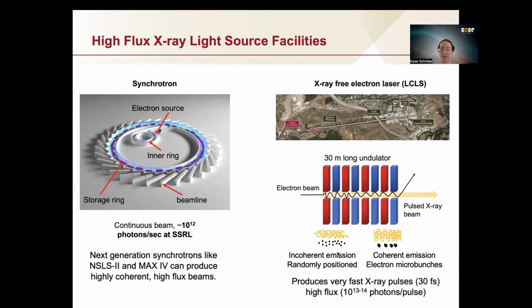What happens when it goes through this undulator is you have incoherent emission of X-ray light and randomly positioned electrons in the beam. As it goes through the undulator, the electric field starts to impart more force onto the electrons and the X-rays, and you start to see coherent emission of X-rays and also electron micro bunches that are spaced evenly. And we call this process self-amplified spontaneous emission. And when this occurs, you can get very, very fast X-ray pulses on the order of 30 femtoseconds. And you get a lot of X-rays in that pulse.